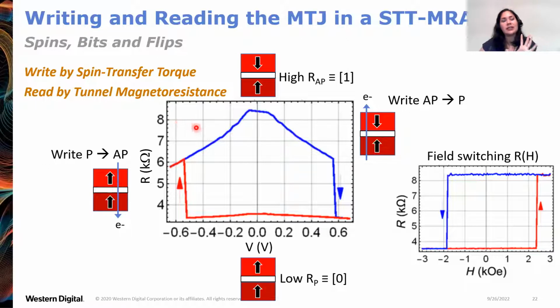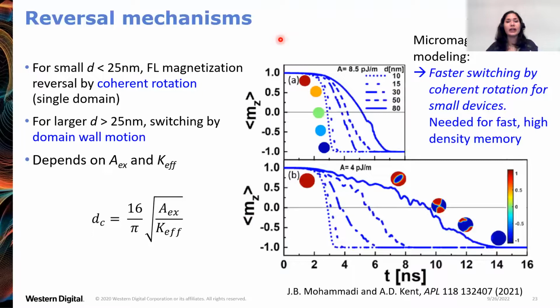If you take this same tunnel junction and, just for demonstration purposes, you want to flip it by magnetic field, then you will get the resistance versus magnetic field curve shown here on the right. Again, these two well-defined parallel and anti-parallel resistance states. And the reversal of the free layer happens by a couple different mechanisms, depending on the size of the bit or the diameter of the bit and the magnetic properties of the free layer.